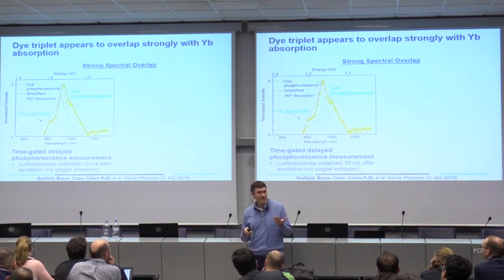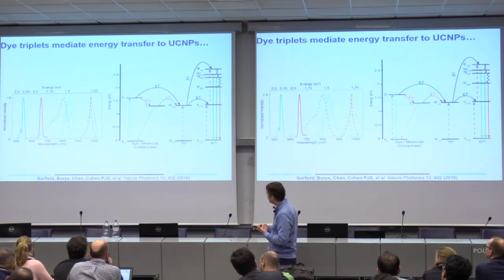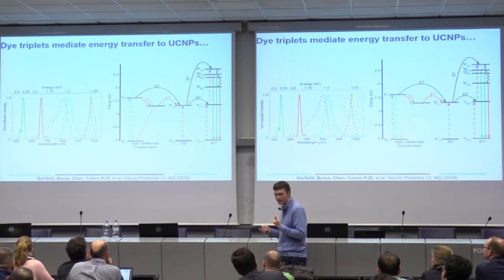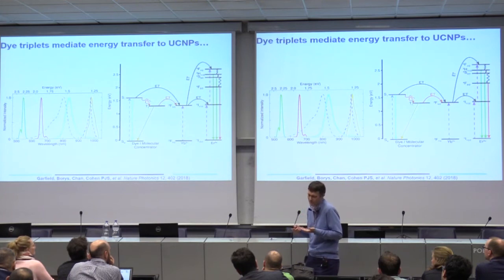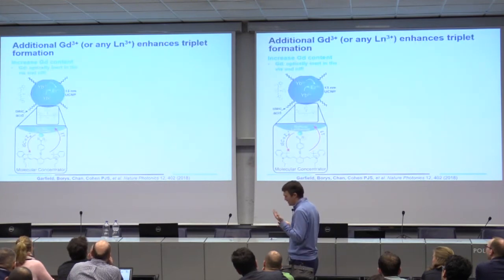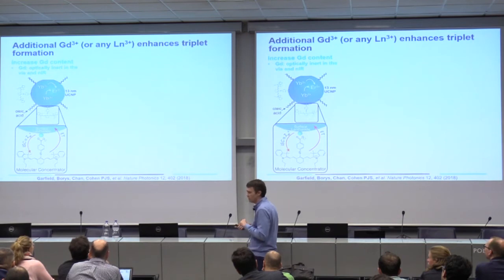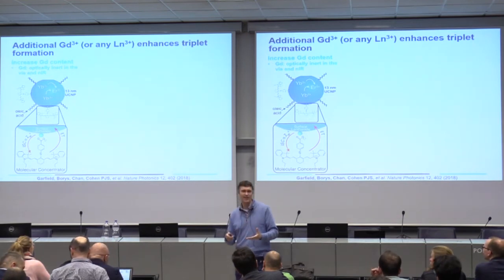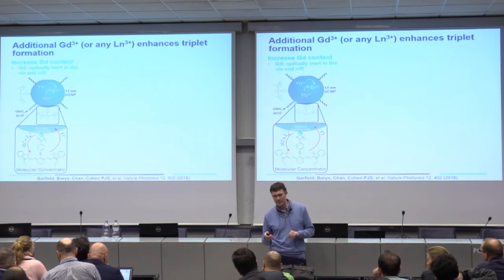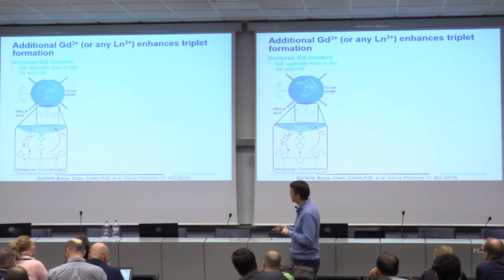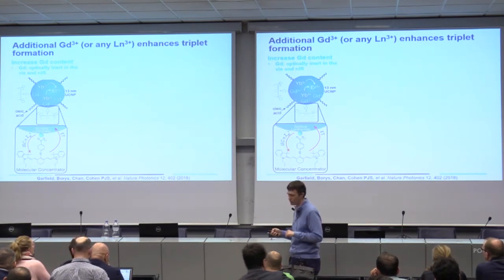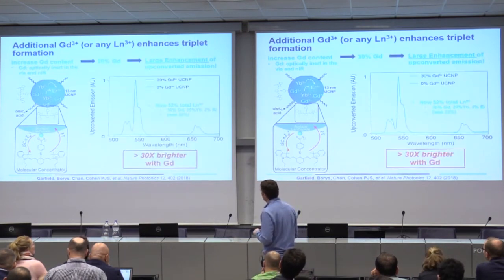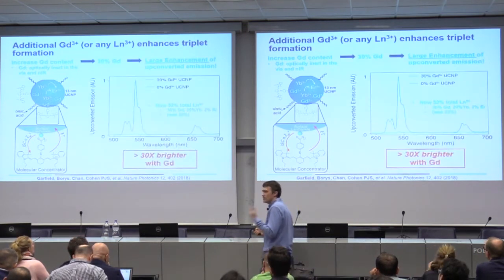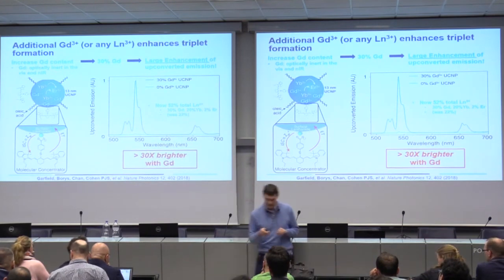We now realize the mechanism for how energy gets from a dye molecule into the upconverter. And in fact, it goes through the triplet. So the question became, well, if the triplet is doing all the work, how can we create more triplets? I'll again save you most of the details, but the short answer is you put more lanthanides in your material, more heavy atoms. And the heavy atoms are what induce this intersystem crossing. And so by increasing the lanthanide content from 20% to about 50%, what we saw is that we got 30 times additional brightness just by engineering our particles that way.